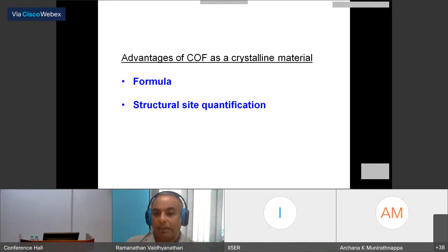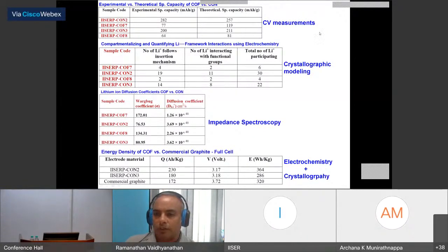And so what is the major advantage of a COF? Another major advantage comes from the fact that it is a crystalline material, which means you can derive a formula for your compound, and also you can get structural site quantification. From cyclic voltammetry and also from the crystal structure, you can calculate the theoretical capacity of your material: how many lithium ions it can have, and based on that number of lithium ions, how many milliamp hour per gram it can give. You can compare it with the experimental value, and they show an excellent match. You can also assess your material's capacity in terms of the number of lithium atoms per specific number of functional groups in the unit cell of your COF. This gives a huge advantage when you want to make a future battery design based on a module approach.